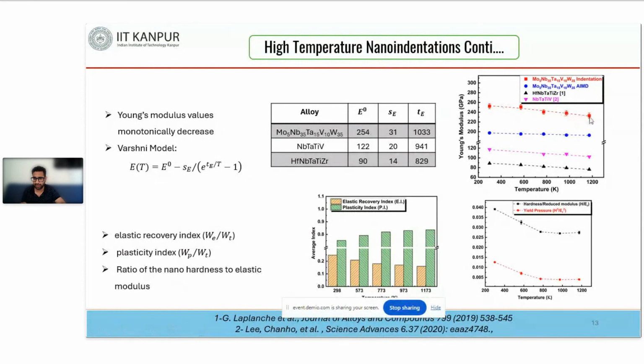In order to compare this modulus value with other alloys, we use the Varshni model, and the alloys studied in the literature are hafnium, niobium, tantalum, titanium, zirconium, and niobium, tantalum, titanium, vanadium alloy. When we compare this alloy with the non-equiatomic alloys, obviously our alloy is going better, giving a better modulus value. We also see there is an SE parameter and a TE parameter. The SE parameter gives you the temperature dependency of Young's modulus, and the TE parameter gives the resistance to thermal effects, that is, the thermal stability. This alloy has a high value of 31 for SE, and the thermal stability of this alloy is high over a wide temperature range.